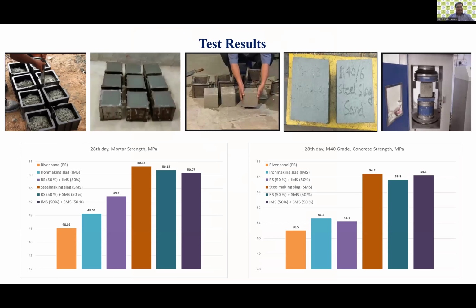If we compare the test results of these aggregates, we find that compared to river sand, both iron making slag and steel making slag individually give better results because of higher density and its more controlled shape. And in combination of these also gives us a good result. So it can be used individually as well as in combination with either of them. And you can see both in mortar as well as in concrete, the 28-day strength of these products are higher than the control sample of the river sand.